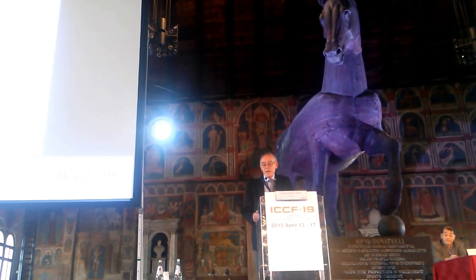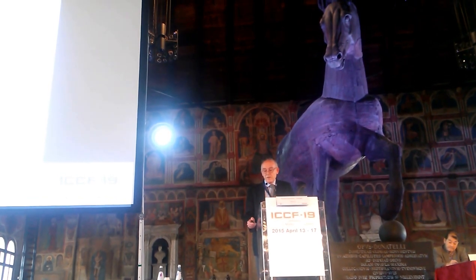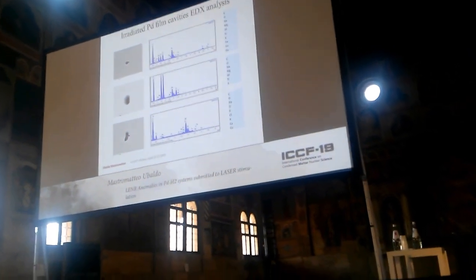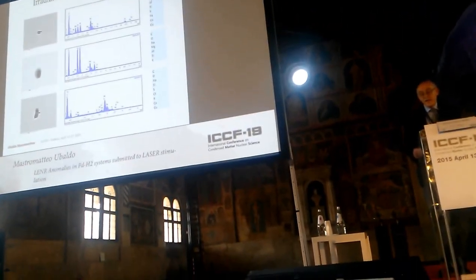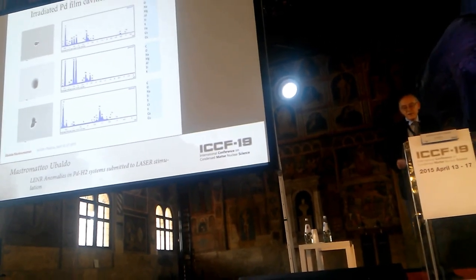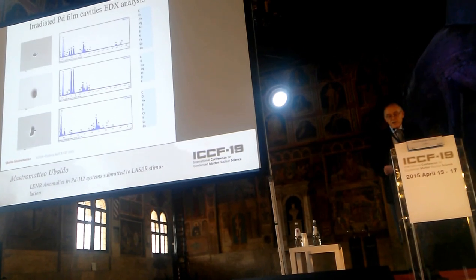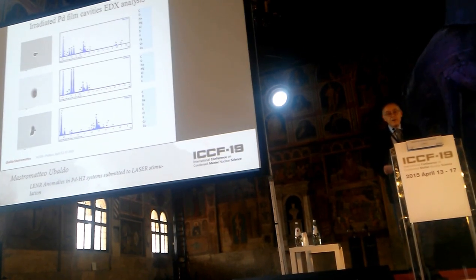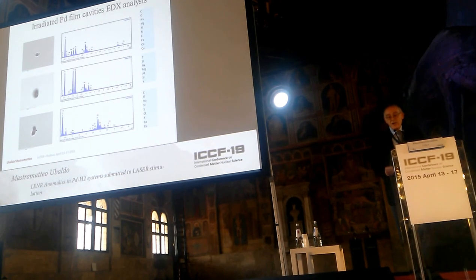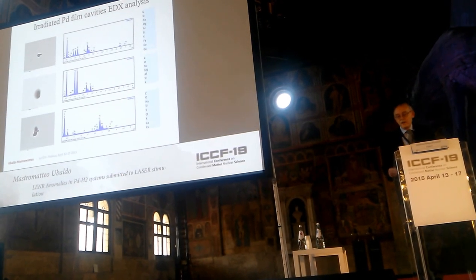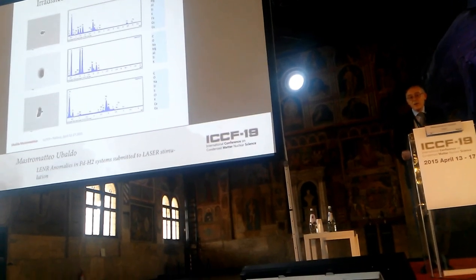And after that, we open the reactor, extract the sample, and we go to SEM analysis to make pictures and to make analysis of eventually elements coming from transmutation. In this case, the samples are very similar to what we used in Lecce, but there is an important difference that I need to mention. To make adhesion between the palladium and the silicon dioxide on the chip, in this case we used chromium. But in the Lecce experiments we used titanium.